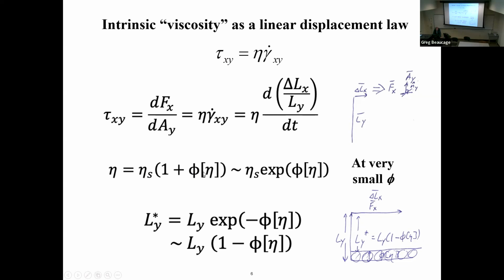this is viscosity, that's viscosity. This term, 1, is unitless, so this term has to be unitless. That thing's units are inverse concentration, not viscosity. So even though it's called intrinsic viscosity, it's not a viscosity at all. What it is is 1 over the overlap concentration. This thing has nothing to do with viscosity, even though it's called intrinsic viscosity.